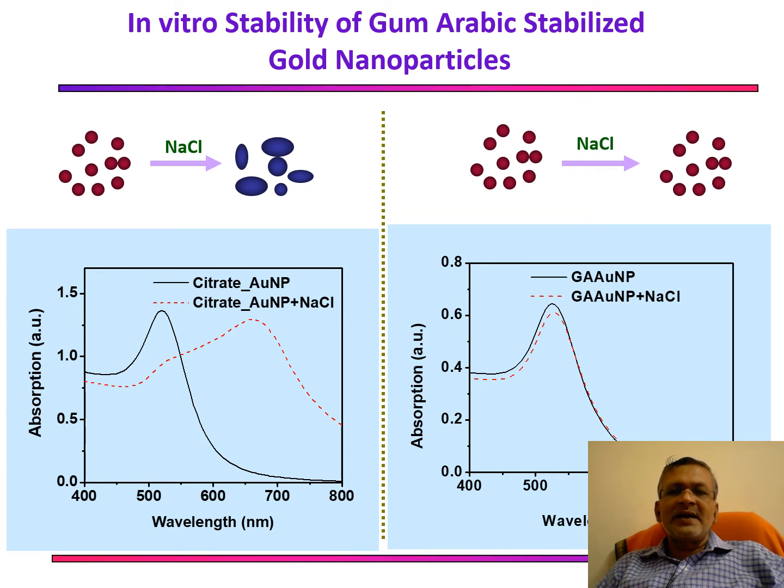This represents that whatever nanoparticle we have synthesized is accurate, and the peak position of 520 nanometer, 540 nanometer, is characteristic of a particular size of the nanoparticle. Therefore, the size of the nanoparticle can also be calculated from the placement of the surface plasmon resonance peak.